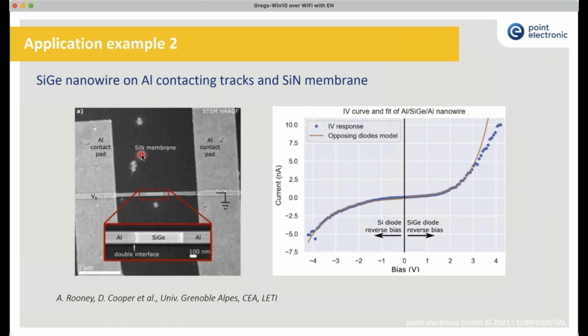It's a silicon nitride membrane. It has two aluminum contact pads. The silicon germanium nanowire is put across, and it's heat treated. By heat treating, aluminum is diffusing into the nanowire, and only in the middle do we have silicon germanium left, and we can see the aluminum diffusion from both sides. And they have done great work looking at the interfaces with high resolution TEM and seeing what those interfaces are. And for example, they see that they're not the same. They're different interfaces on both sides.